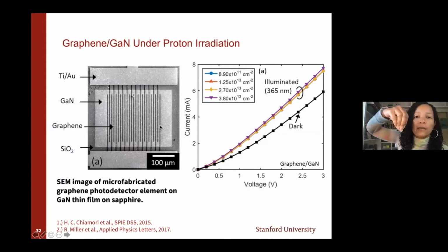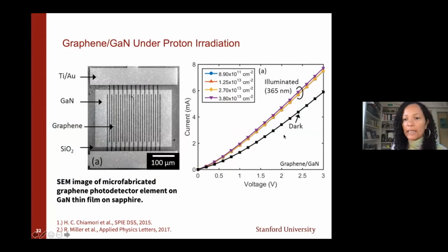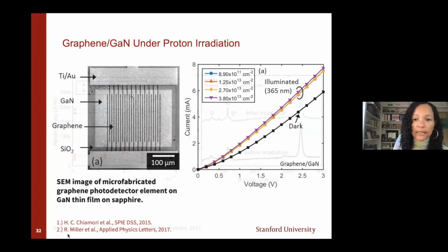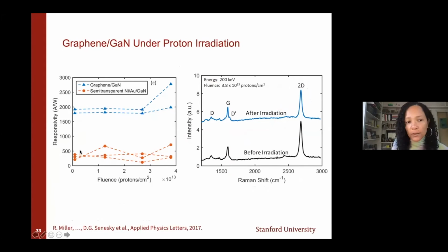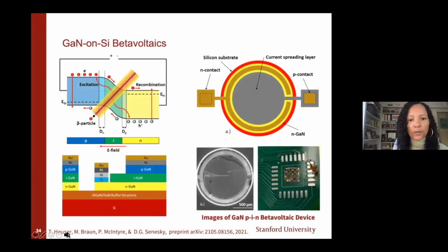So when a photon comes in, we generate an electron, and we can measure the current, dark current, light current, and then continue to measure that over different irradiation fluences. And we see quite stable responsivity in our elements. And then also we measured the Raman profile of the graphene after the irradiation. And so this is showing the presence of the common D, G, and 2D peaks. And then after irradiation, we see this little D prime peak, which is conveying there is some degradation in the graphene. However, nonetheless, it's still working.